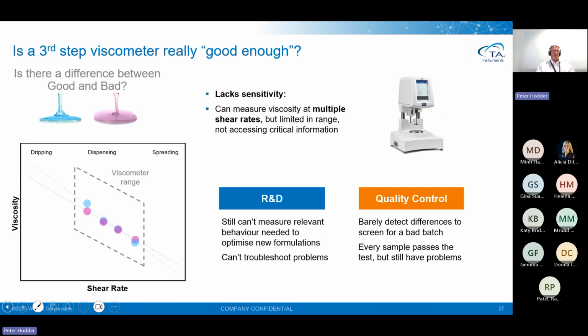And what we see is the viscometer range does show a trend of the samples showing shear thinning. The viscosity is dropping as you're increasing shear rates. However, you can't really get a very wide shear rate range. So we still can't predict what the sample might be doing at spreading or dripping. All we're doing is maybe extrapolating, assuming it's like a straight response. So we still can't really measure the relevant behavior needed to optimize our new formulation for storage or for applying. We can't troubleshoot some of the problems as a result. And we can still really barely detect differences between our good and bad batches.